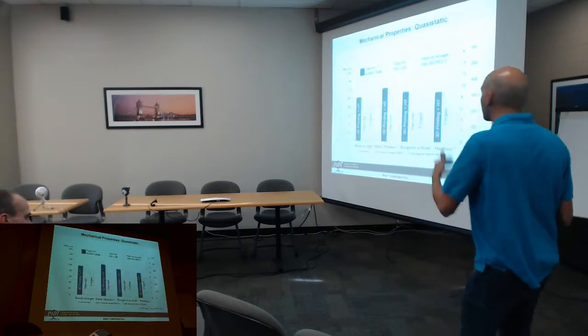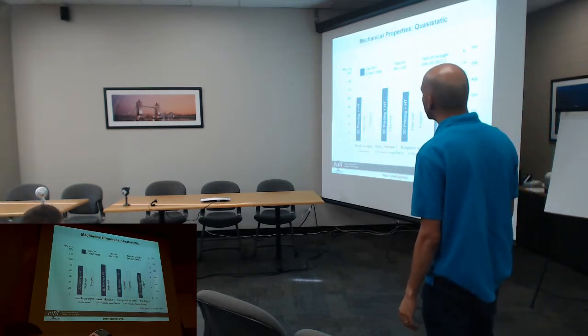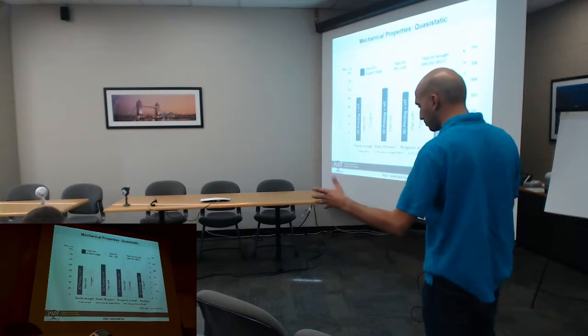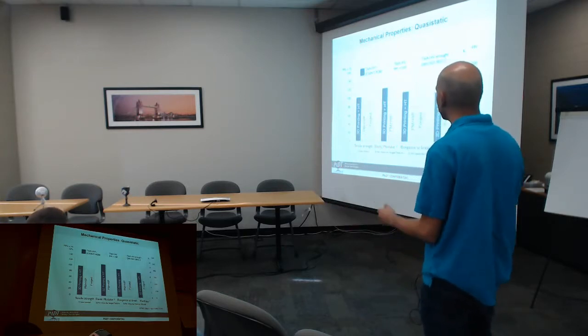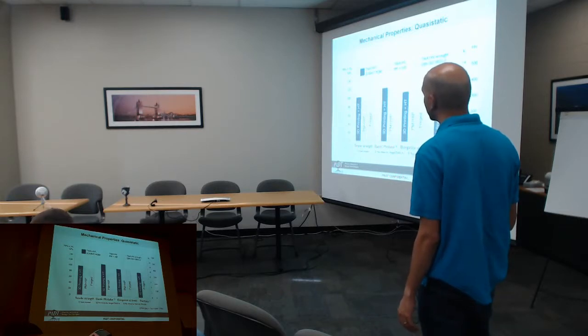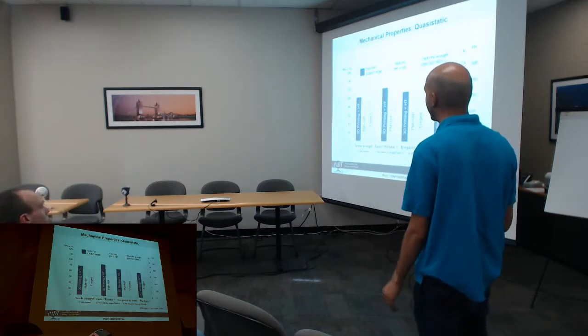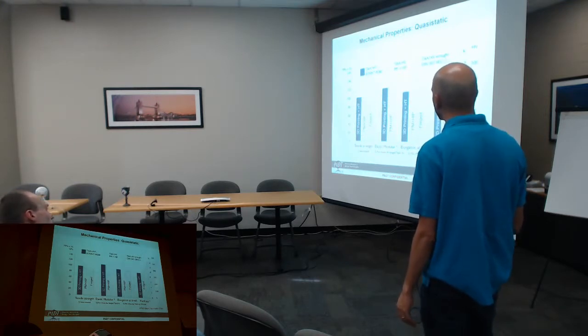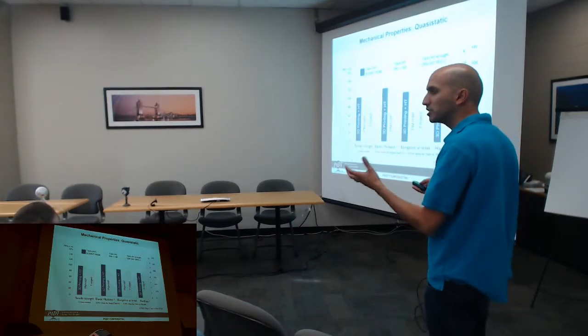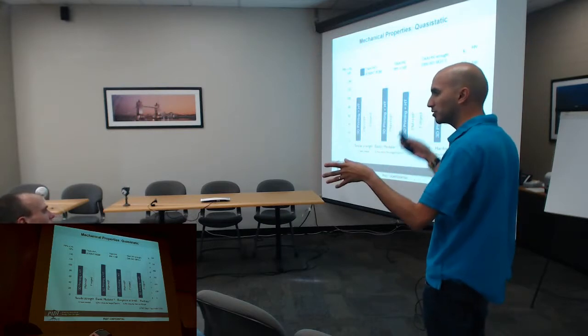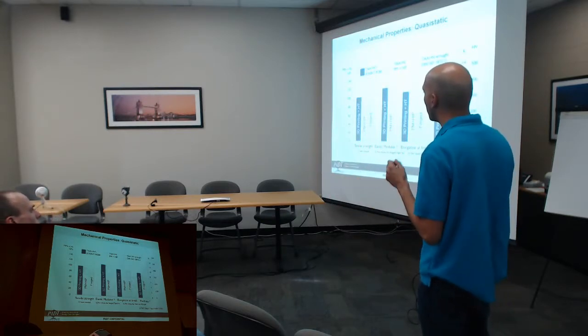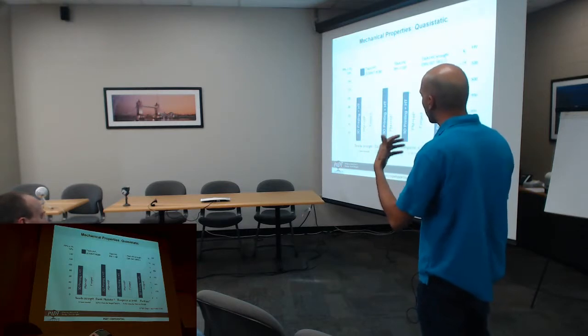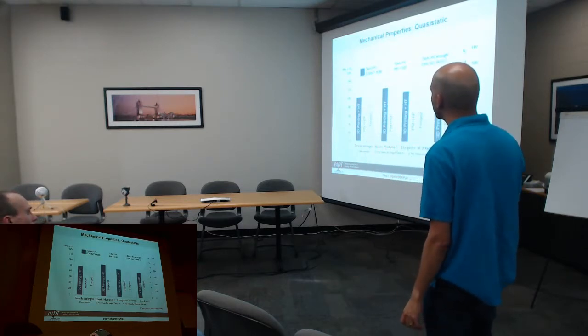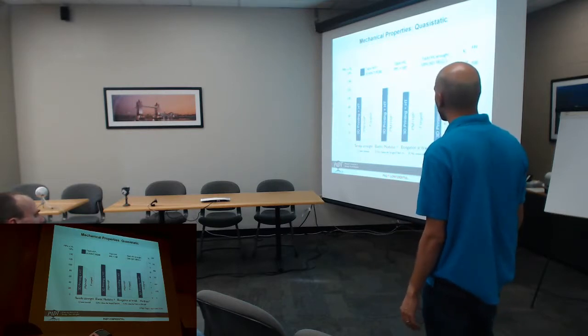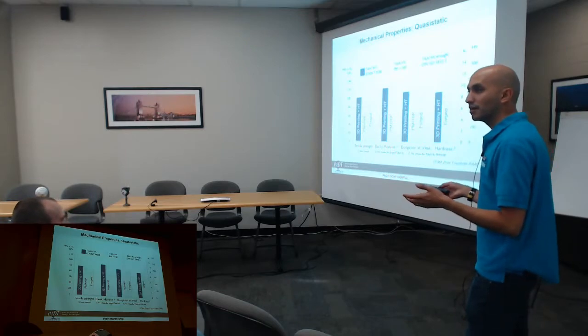If we look at the mechanical properties arising from this, going back to that question, here is conventional forged. So you'd bring a piece of metal and smack it till you got the piece that you want, and this is what people have shown with 3D printing, followed by a heat treat, for tensile strength, for elastic modulus, for elongation at break, and for hardness. And this in the middle is the powder metallurgy, because it's sort of an apples to apples comparison. Both are starting with powders. This is using the conventional powder metallurgy process with something called a hot isostatic press afterwards. So we've got 3 different processes, and 3D printing is very comparable for these mechanical properties that are listed over here.